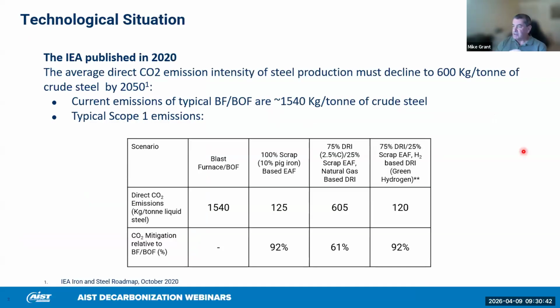You've all seen tables like this. The blast furnace is the big villain in today's society, producing 1.5 tons of CO2 per ton of steel produced. And this compares with 100% scrap-based electric arc furnace steelmaking, which is about 125 kilograms of CO2 per ton. These are direct emissions, emissions from the process itself. And we could look also over at the hydrogen-based DRI process with the EAF at roughly the same amount of emissions. So both methods for producing steel reduce CO2 emissions by about 90%, scope one, and certainly these are the obvious choices for future low carbon steelmaking.